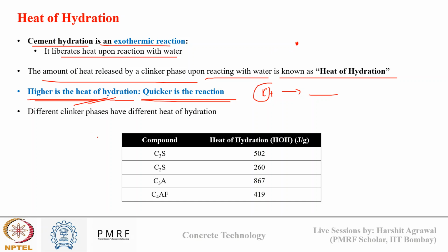Okay. Now, different clinker phases have different heat of hydration. Okay. C3A has the maximum heat of hydration. Then C3S is at the second position. Then we have C4AF, and the least heat of hydration is of C2S. Why? Because C2S is stable compared to C3S and C3A. So it takes time for C2S to react with water, and that's why the heat of hydration is also lower, because it reacts slowly with water. While C3A reacts rapidly with water, and that's why heat of hydration is also high in case of C3A.